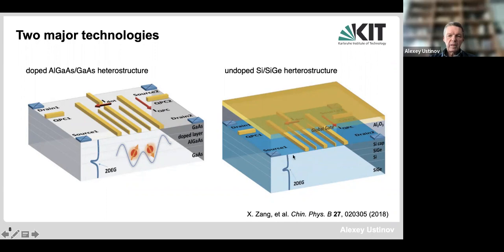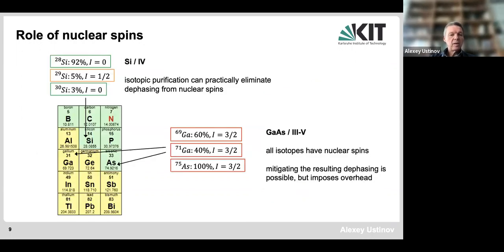Now, this technology was developed a bit later. I think now they also can show very high mobility, but there is a tremendous advantage of silicon germanium heterostructures relative to gallium arsenide heterostructures, and this is due to the spin states of the underlying structures. For gallium arsenide, the natural mixture of gallium and arsenic consists of isotopes which have nuclear spins, and while mitigating the effects of these spins of the matrix crystal is possible, it really limits very significantly the spin coherence of the spin dots. You have some random noise of the nuclear spins around.